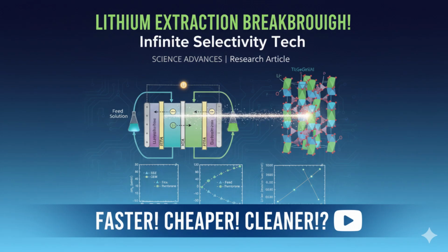Huh. Okay, so who's the bouncer at this atomic nightclub? What determines who gets in? Is it just size? Size is a huge part of it. The study talks about the specific structure of these Nasicon materials. They have these conduction channels, these pathways for the ions, but they have very narrow bottlenecks. How narrow? They estimate the critical size, the tightest squeeze point, is between about 1.8 and 2.0 angstroms. Extremely tiny. Now, a bare lithium ion, Li+, has a crystallographic radius that's small enough to just fit through that bottleneck. But a bare sodium ion, Na+, which is the next most similar competitor, it's just slightly larger. Large enough to not fit. Large enough that it's effectively blocked. It's physically too big to squeeze through that 1.8 to 2.0 angstrom gap. So size exclusion is the primary bouncer keeping sodium out.